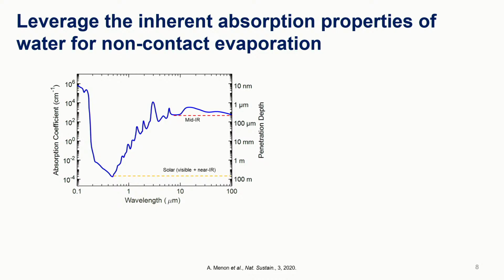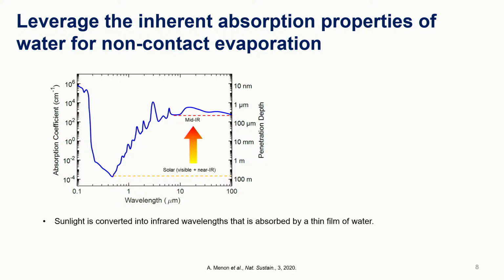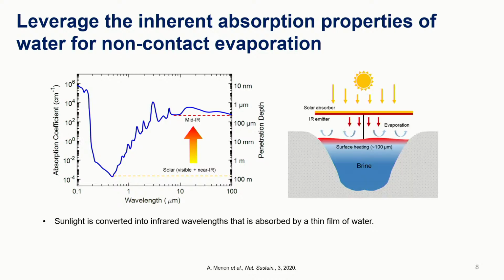So here I'm showing you the absorption profile of water, and we see that around the solar wavelengths, here in the visible range, water has a very low absorption coefficient, which means that it's not going to absorb sunlight strongly. But if we convert that sunlight into mid-infrared wavelengths, you can see the absorption coefficient increases significantly, and all of that sunlight can be absorbed within a few microns of the water, so really just the surface. So what we do is we convert this visible and near-infrared sunlight into mid-infrared in order to increase the absorption, and now we can rely on just using thermal radiation.